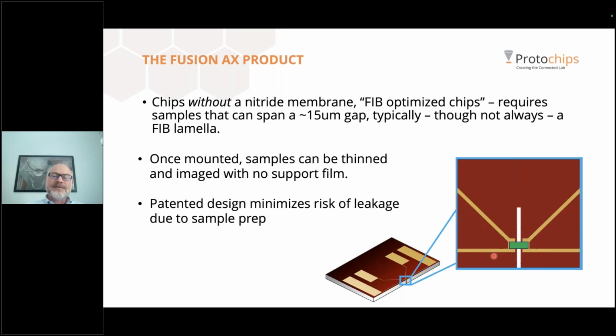Larger samples, including FIB lamella, have another option. We call these the FIB optimized chips. Here the sample is mounted over a gap and connected to electrodes on either side of the gap. Once it's mounted, the sample can be thinned in place and then imaged and characterized in place. This design was created to solve a common problem with FIB metallization, the deposition of metal around the sample. I'm going to talk more about that in a moment, but these are the 2 types of chips that we offer: chips with electrodes on membranes and chips that have electrodes beside a gap.